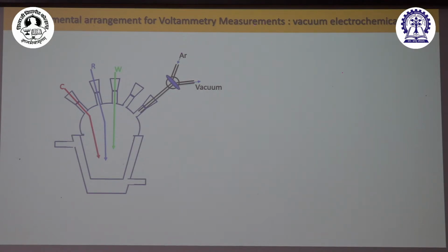This is a cross section. There are 5 ground glass joints on the electrochemical cell, and there is a jacketed cell. You can see the jacket. What we did here, we added the electrodes. You can see there is a counter, reference, and working electrode. There is an argon and vacuum two-way gas line, and then we added the supporting electrolyte, which is TBAP. We need a supporting electrolyte in electrochemistry to make the solution conducting.